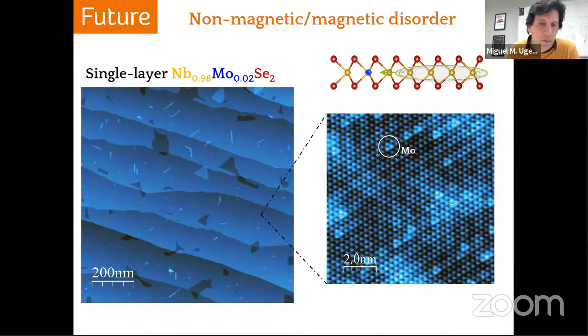features coming from the confinement. But if you make the numbers for the system, the coherence length of the system is about 100 nanometers, which is not small at all. But basically, we are using samples like the one you see here. This is a good sample where the NbSe2 is continuous. So of course, these steps that you see here are coming from the silicon carbide, but the system is continuous. So in principle, there are no boundaries confining the material.